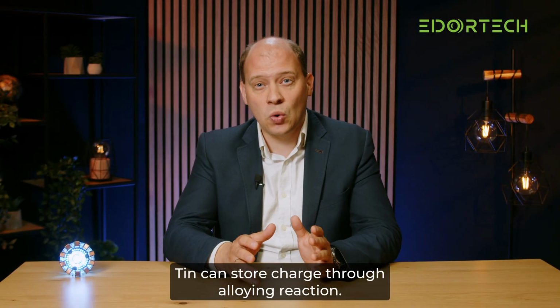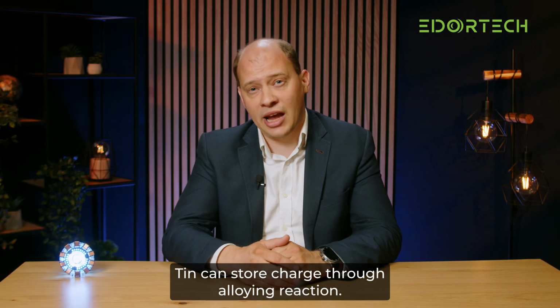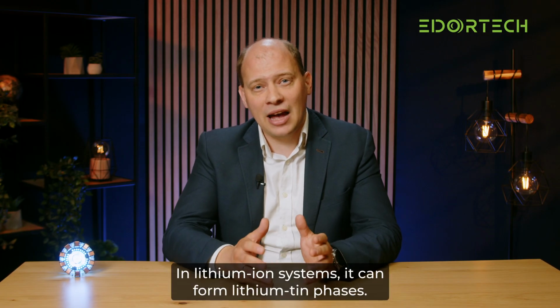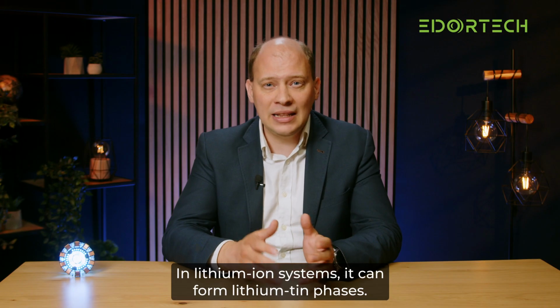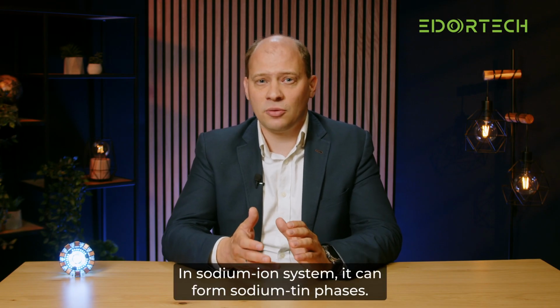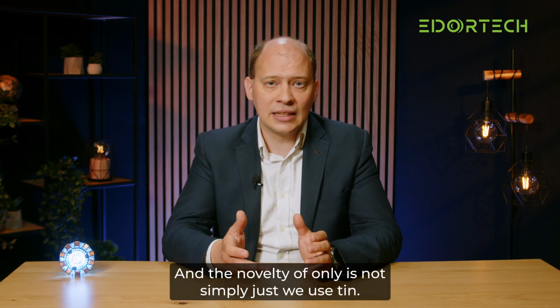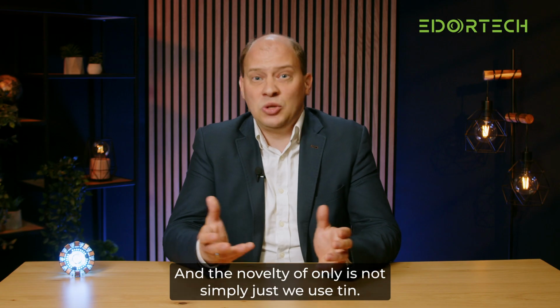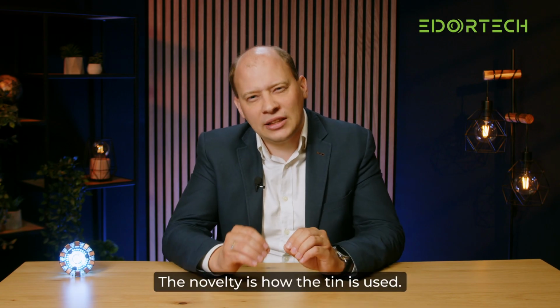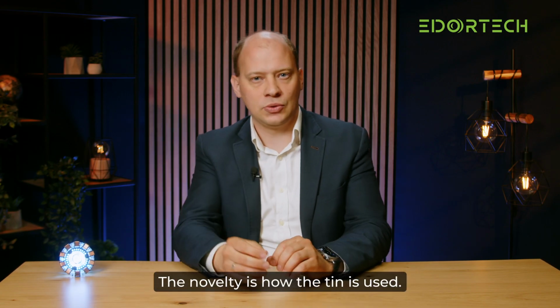Tin can store charge through alloying reaction. In lithium-ion systems, it can form lithium-tin phases. In sodium-ion systems, it can form sodium-tin phases. And the novelty of ONLi is not simply that we use tin. The novelty is how the tin is used.